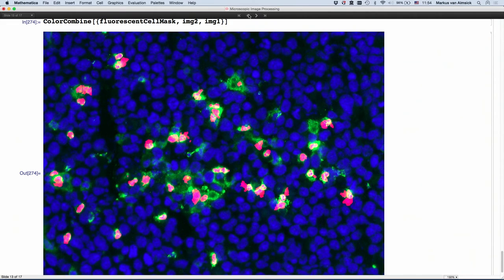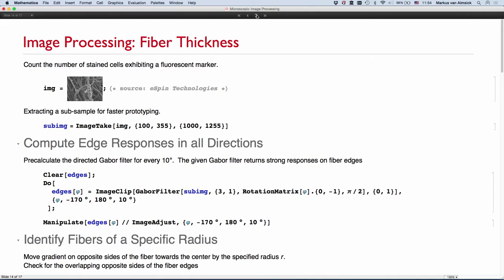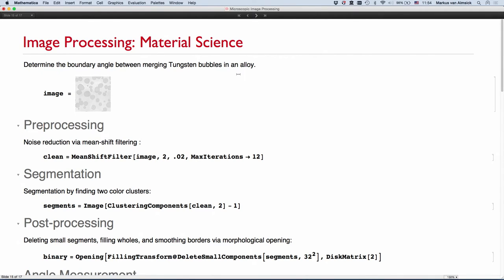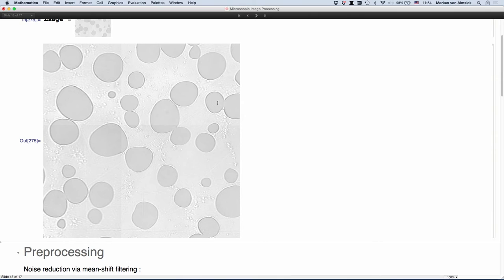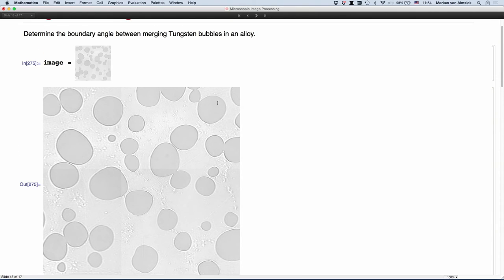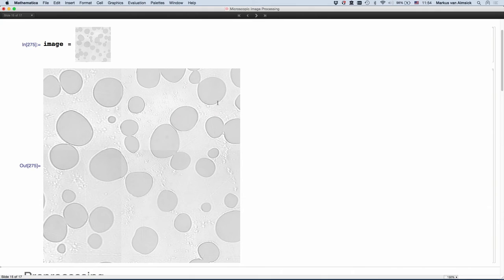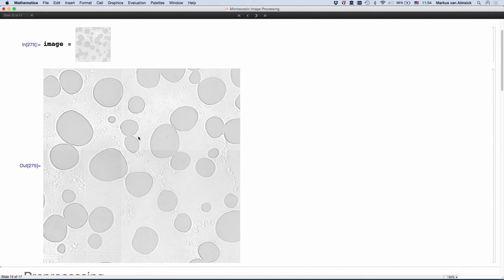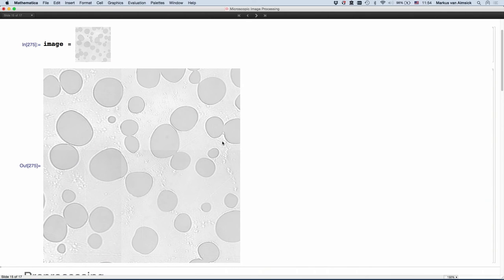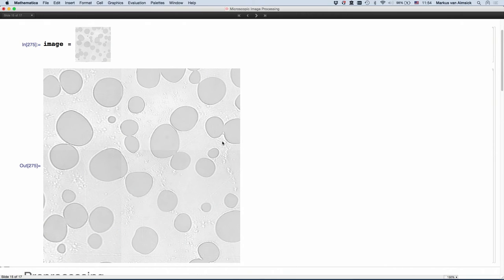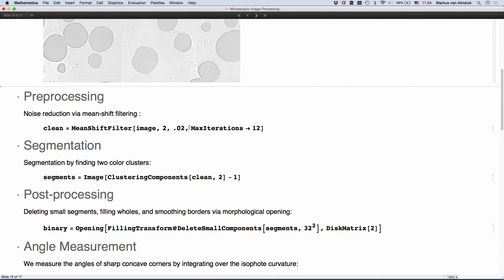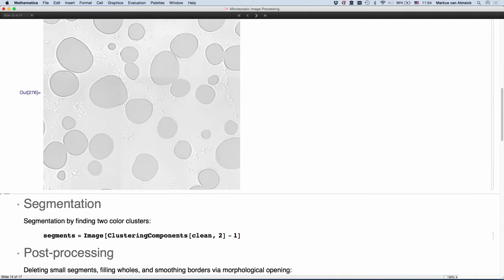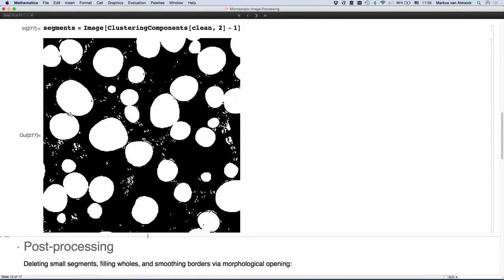One more application. This I'm going to skip. This is an application or problem from material science. It's rather awkward. It basically gives you these kind of pictures. And what you see here is an alloy. And the bubbles, they are tungsten bubbles. And an alloy, I forgot which it is exactly. And to deduce certain material properties, you have to find the angles between merging bubbles. So you have to measure the angle here and here and so forth. And this is a rather tricky thing because depending on what resolution you look at this, the angle does change. So you have to specify, we can only do this measurement properly by defining a specific scale and then doing that measurement at that scale. And I do this measurement, well, before I do the measurement, I just clean up the data a little bit with the median filter, segmenting the thing, deleting all the tiny segments. And then I basically now have the bubbles defined.